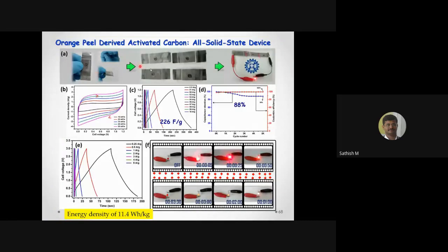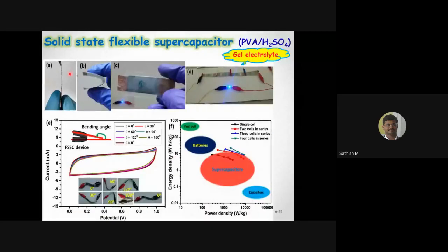We made a very tiny supercapacitor, maybe 2-3 years before. We made 2-3 small capacitors clubbed together, and we were able to light some LEDs. The advantage of these capacitors is that they are highly flexible in nature. So you can bend this capacitor to 30 degrees, 60 degrees, 90 degrees, or 120 degrees and you get similar performance.